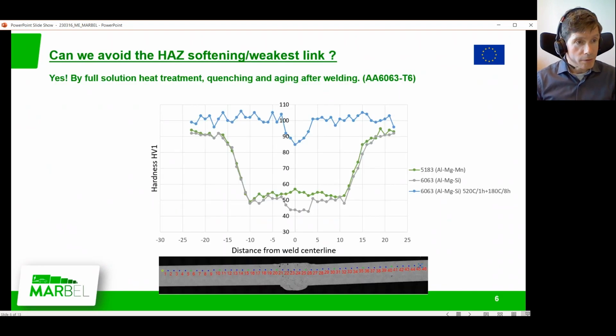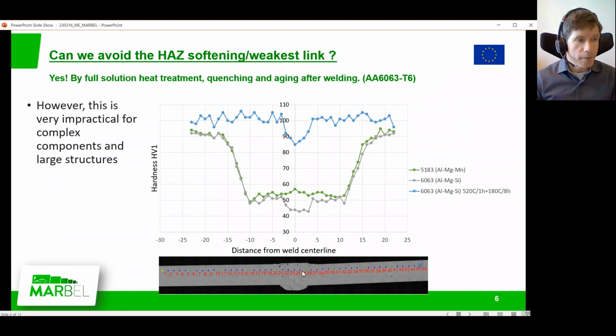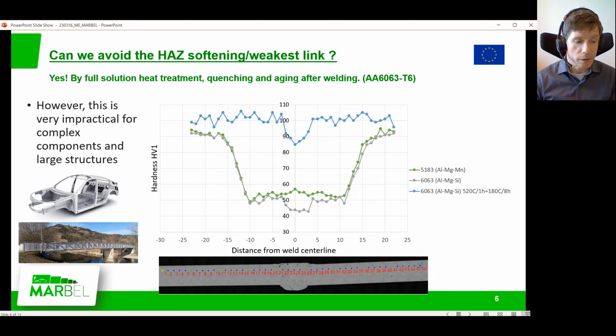So can we avoid this? Yes, we can do it by a full solution heat treatment, quenching and aging, and that has to be done after welding. The blue line here represents a material weld where we have put everything into an oven again and made the full solution heat treatment and precipitation hardening. And then everything is recreated as long as we use the same material in the welding. However, this is very impractical for complex components and large structures, such as full body car components or aluminium bridges like we have here. So this is a very difficult way to go.